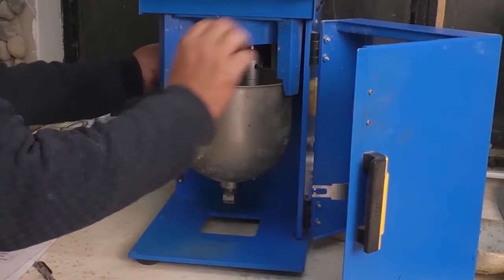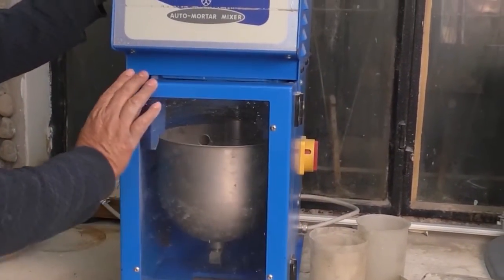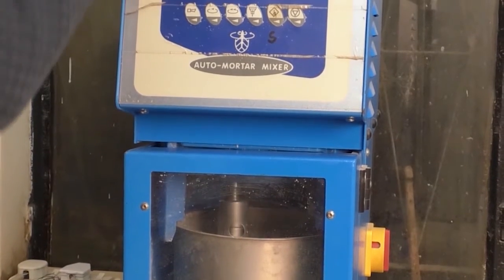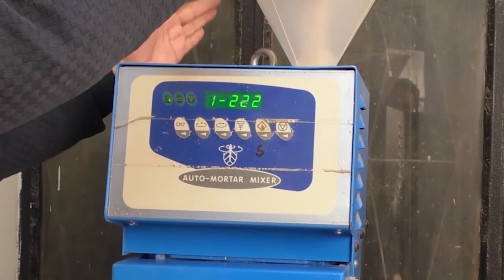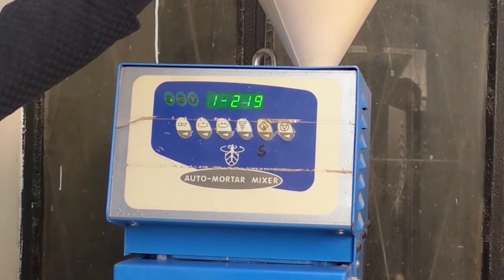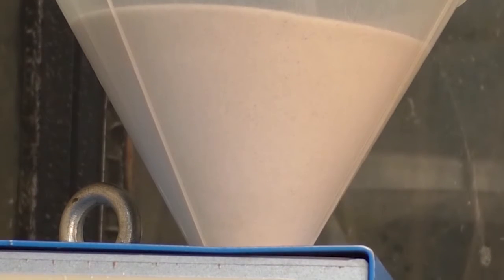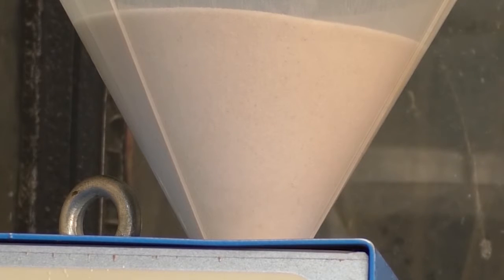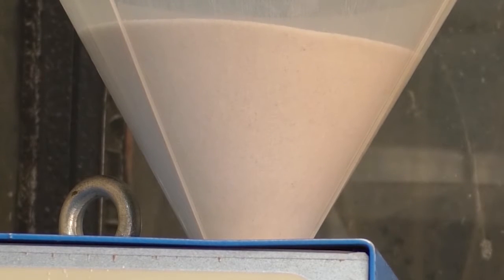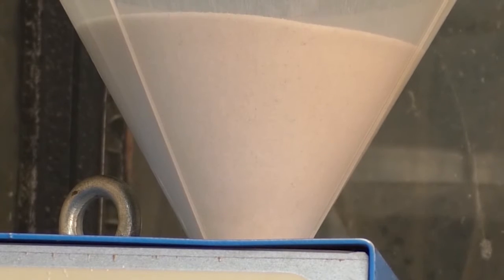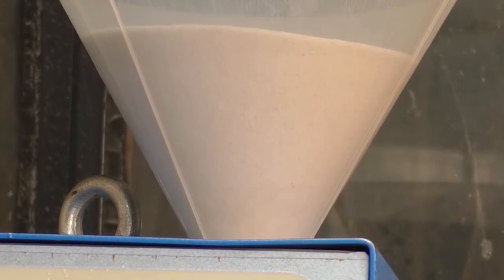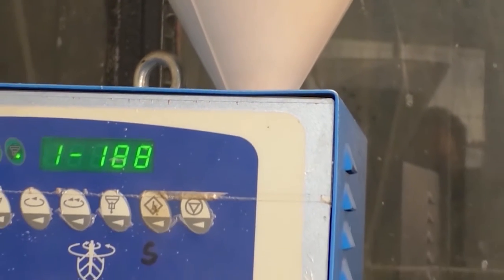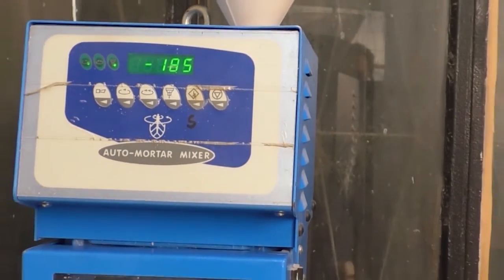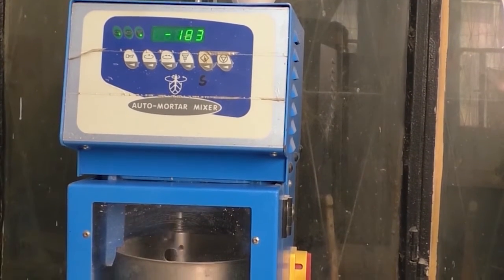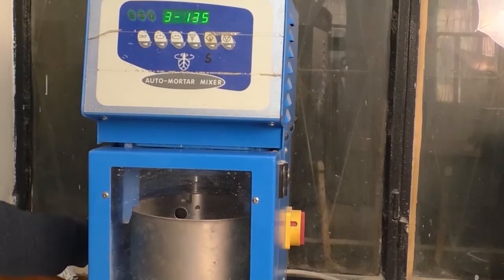Now we have started the mixer and we are mixing at slow speed for 30 seconds. In the meantime, we are adding the entire quantity of the sand into the top feed of the mixing machine so that it can be added to the mixer over a 30-second period of time. After mixing this at slow speed for 30 seconds, we have to mix it for another 30 seconds at medium speed, and after 60 seconds, we have to stop the mixer and let the mortar stand for 90 seconds.